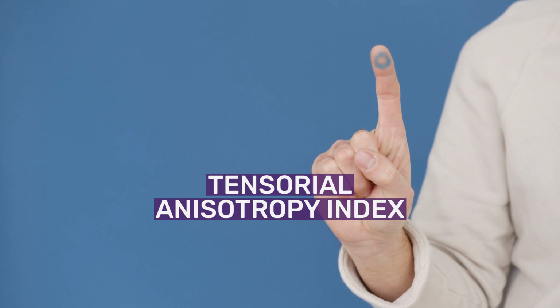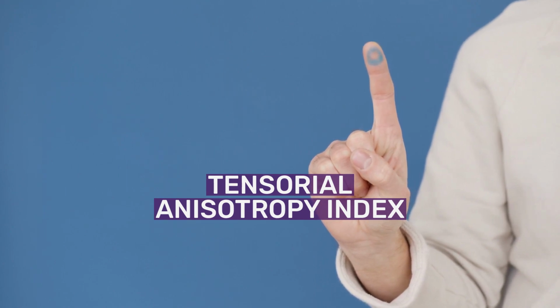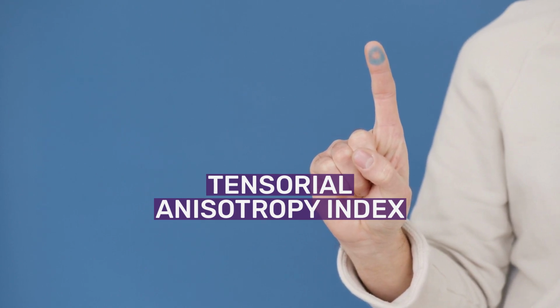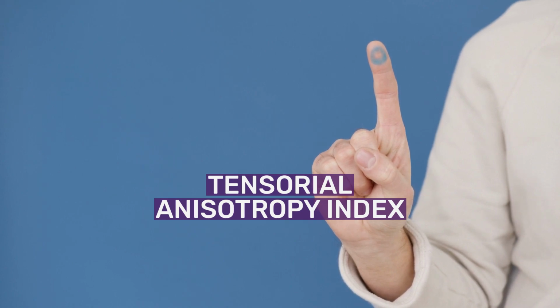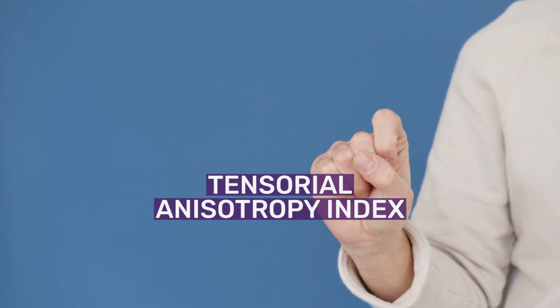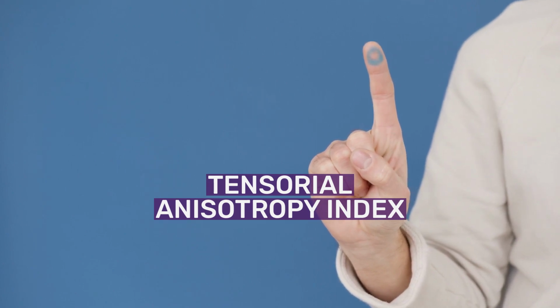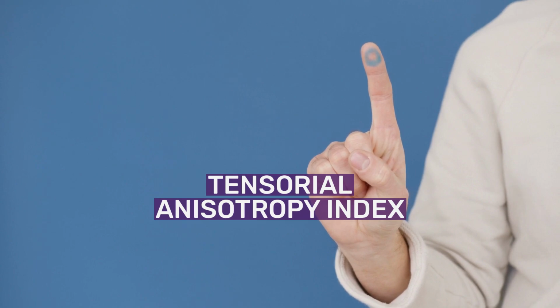In cubic materials, each stiffness component in groups 1-3 has equal value, and thus this expression reduces directly to the Zener ratio for cubic materials. The second component of this index is non-zero for complex materials or composites with only few or no symmetries in their internal structure. In such cases, the remaining stiffness coefficients joined in 3 groups are not null: Cg4, Cg5, Cg6.